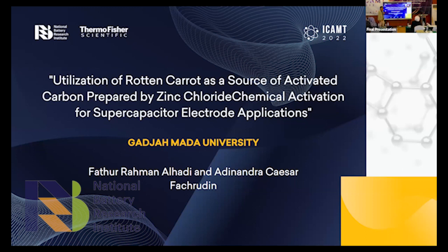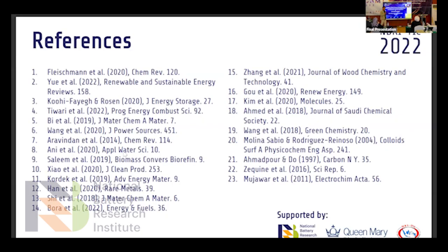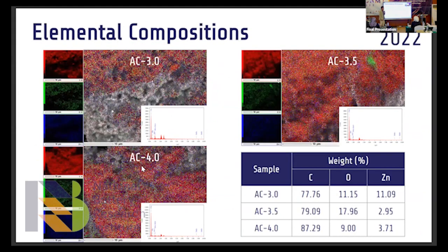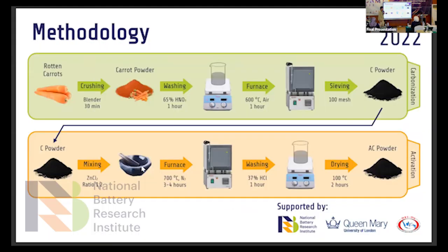So you did the experiment with the parameter of time, right? Yes, activation time. You use 3 hours. So where do you make this 3 hours: in the furnace, the calcination, and then the rest the same? You go from crushing, 1 hour furnace, sieving, and then where is the 4 hour? I'm just doing it in this activation in the furnace with nitrogen atmosphere. Only that, but the rest is the same.